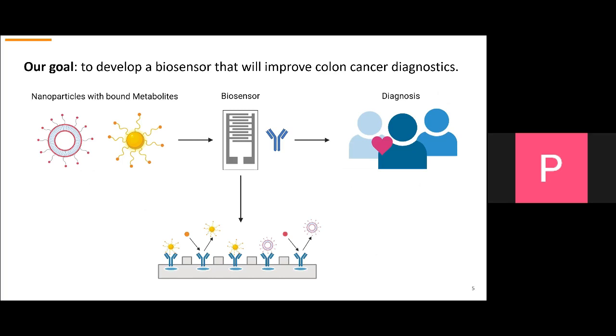The biosensor will test for the metabolites mentioned previously in urine samples, and they will use nanoparticles that are decorated with these key metabolites and antibodies bound to an electrode. It will be a competitive assay where these nanoparticles will compete with free metabolites in a patient's urine sample to bind the antibodies. This will cause an electrical change, which is an impedance reading, and we can use this to determine the concentration of these metabolites in a urine sample.